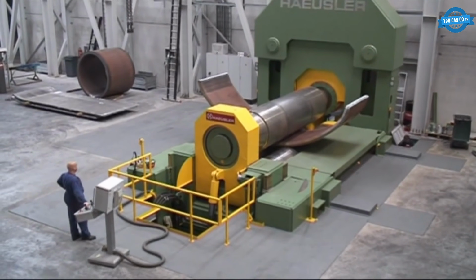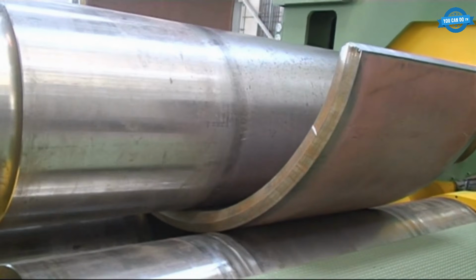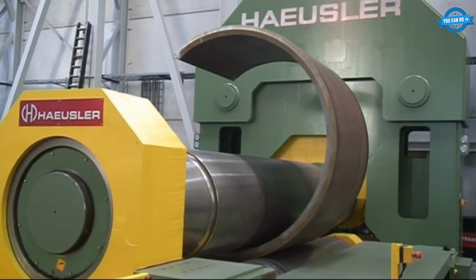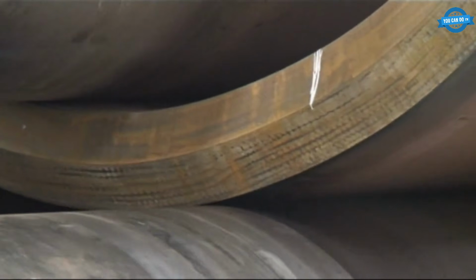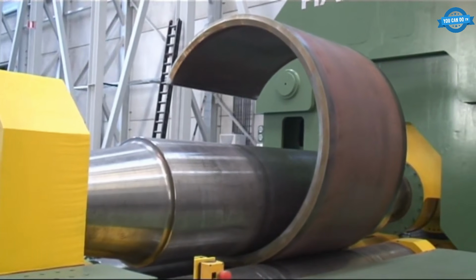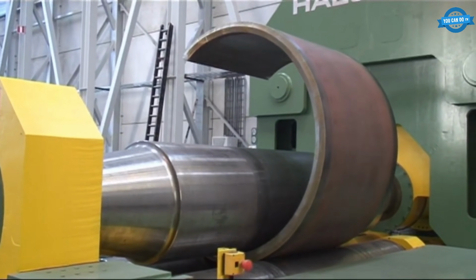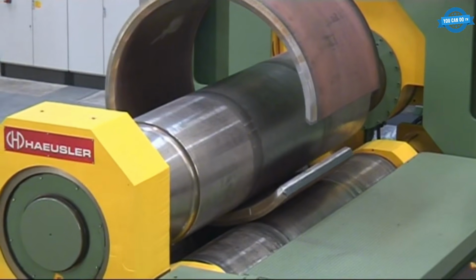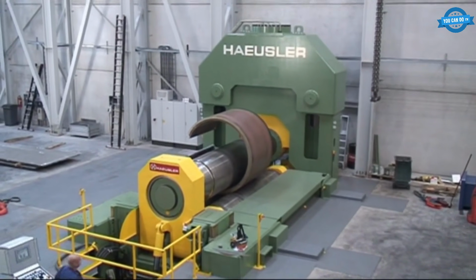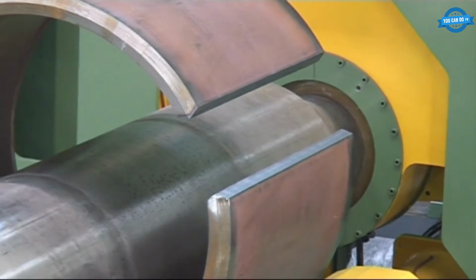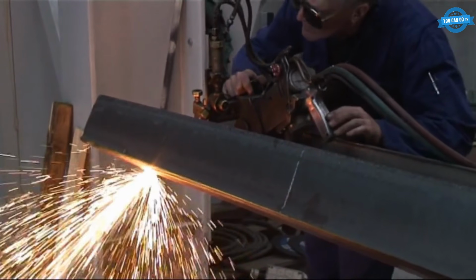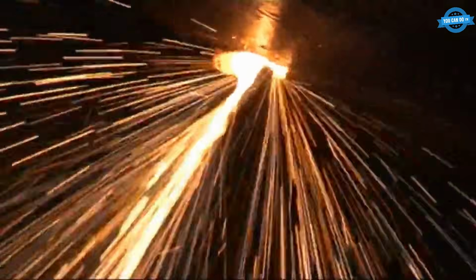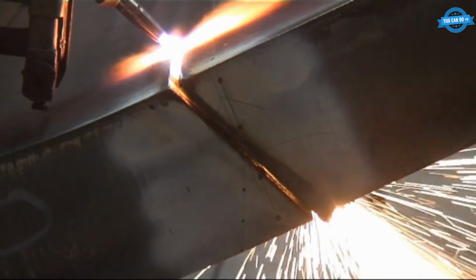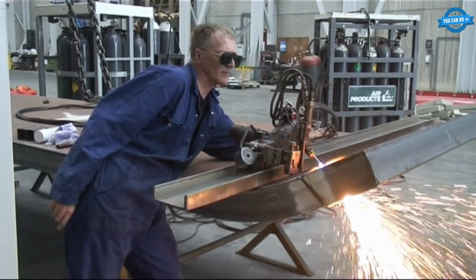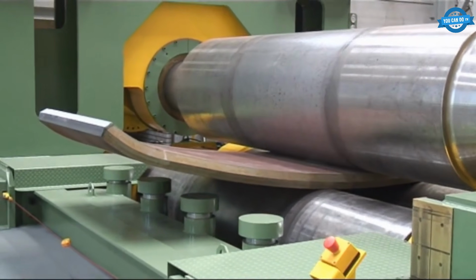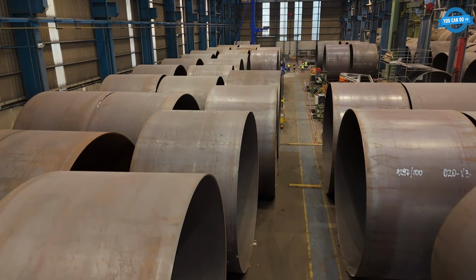How big can a single rolling machine actually get on the shop floor today in real life? This 320-ton 3-roll Haeusler is installed on a custom foundation deep enough to anchor the machine against its own working forces under full pressure operation. A 43-ton steel plate, 150 millimeters thick and 2,230 millimeters wide, rolls down to a finished cylinder 5,000 millimeters in diameter. Edge preparation comes first. Both sides get trimmed and beveled so the seam closes clean. Submerged arc welding then fills the joint with 2 wires feeding simultaneously, doubling deposition speed and finishing the seam in half the time.